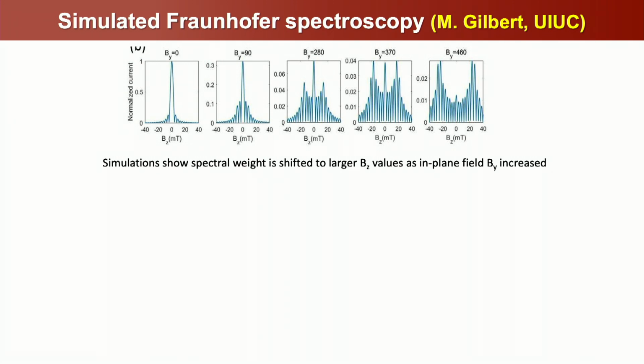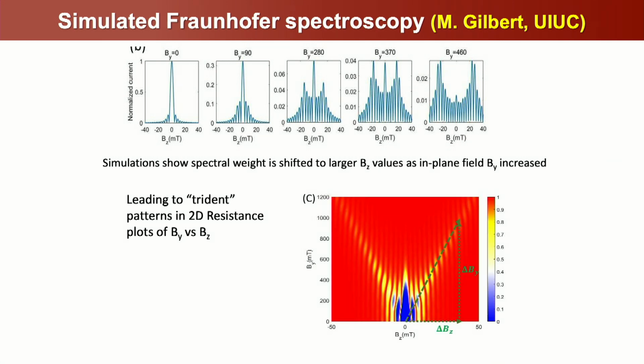So when we measure this, this should lead to 2D resistance maps where blue is superconducting and these are all the colors you see are superconducting and red is normal state. You should see a trident pattern of the superconducting resistance as a function of out-of-plane field and in-plane field.